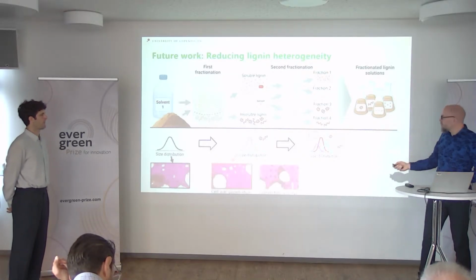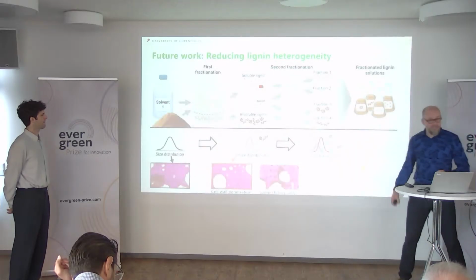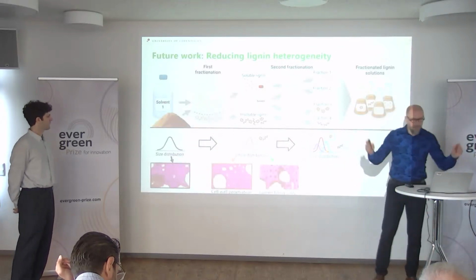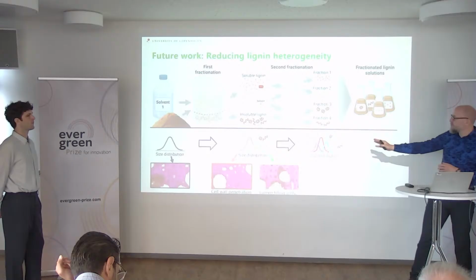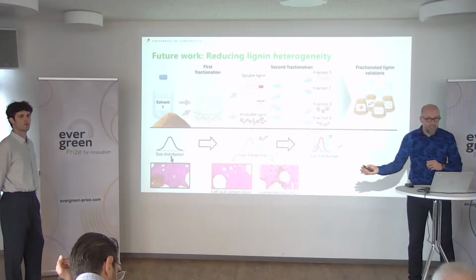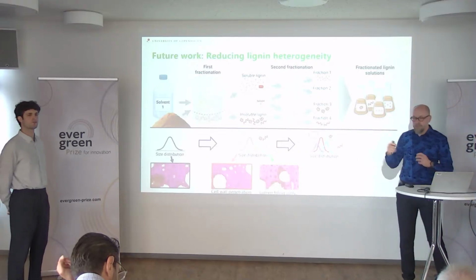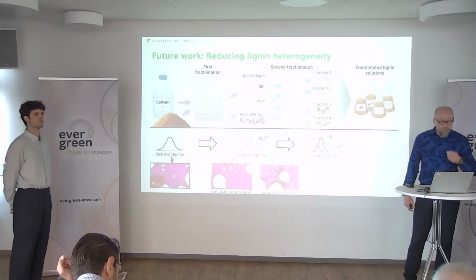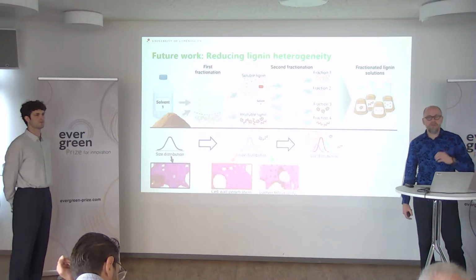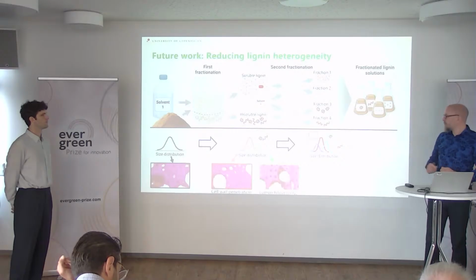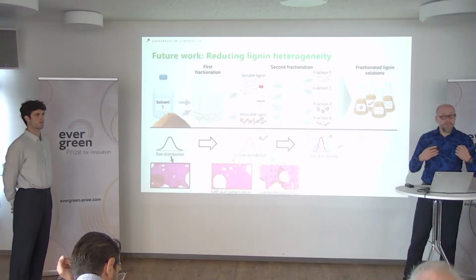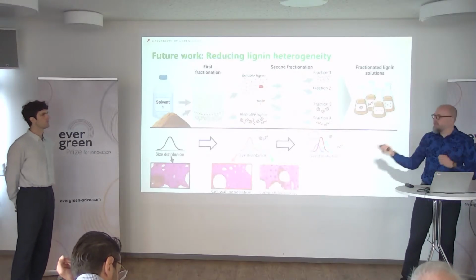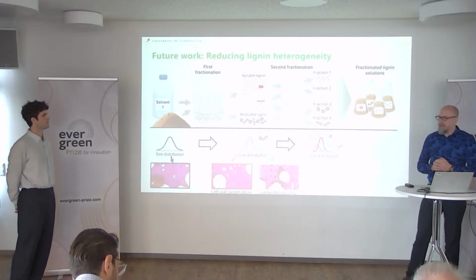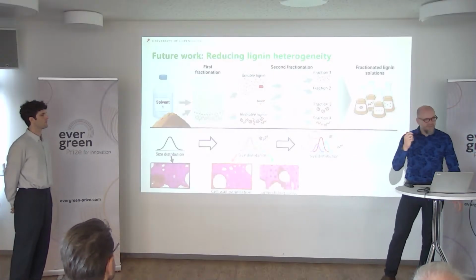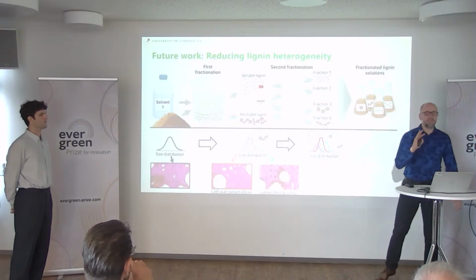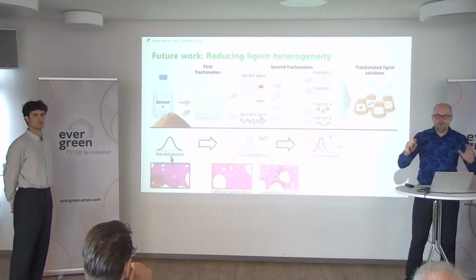And we did it once actually, where we just split up this paper lignin into two: small molecules and large molecules. And what we saw was interesting, because the small molecules penetrated the cell walls, but did not fill up any lumina. Whereas the large molecules only filled up the lumina, but did not penetrate the cell walls. So we have these two different effects that Andrea was talking about, where you fortify the cell walls as well as provide a physical barrier to fungi in the pore structure.